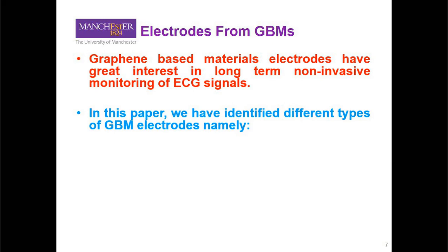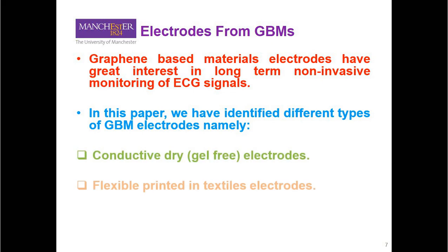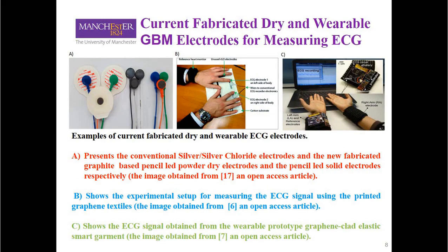In this paper, we have identified different types of graphene-based material electrodes. Those are conductive dry gel-free electrodes, flexible printed-in-textile electrodes, and finally the graphene tattoo electrode. The following graph shows examples of the currently fabricated dry and wearable electrodes. Figure A presents the conventional silver chloride electrode and the newly fabricated graphite-based pencil lead powder dry electrode and the pencil lead solid electrode.